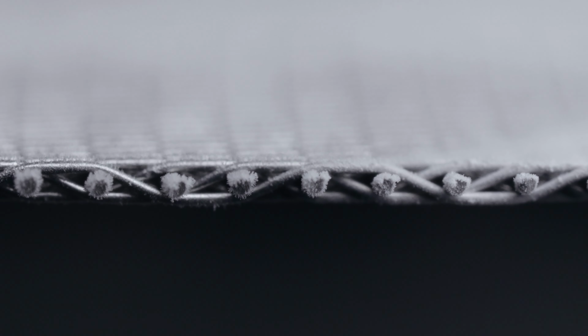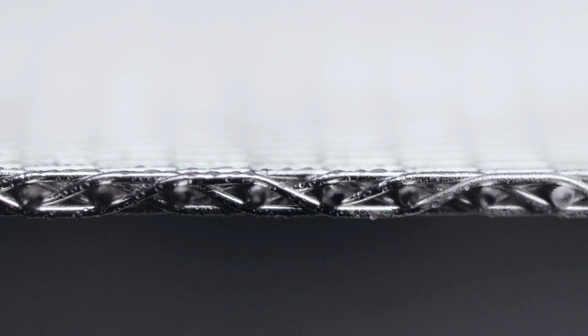Hot gas filtration systems operate across a wide spectrum of temperatures, each presenting unique challenges and requirements. These systems typically process gas temperatures ranging from 260 degrees Celsius, 500 degrees Fahrenheit, to as high as 1000 degrees Celsius, 1832 degrees Fahrenheit, depending on the industry and application. The surrounding atmospheric conditions, which are often between 0 degrees Celsius and 40 degrees Celsius, 32 to 104 degrees Fahrenheit, create significant thermal differentials that can stress filtration components during startup, shutdown, or surprise system events.